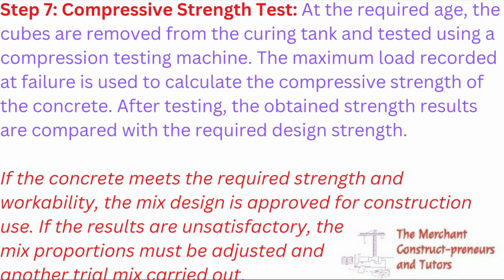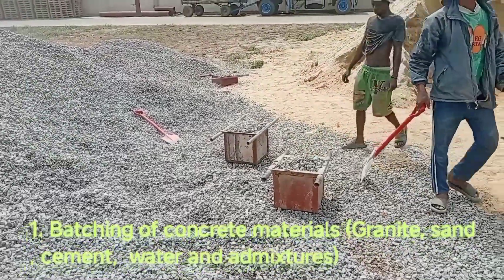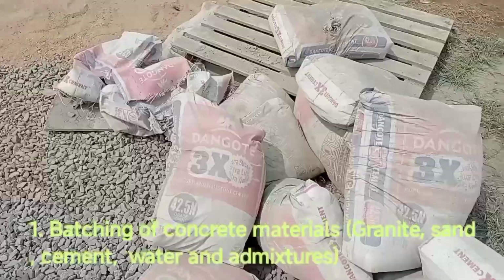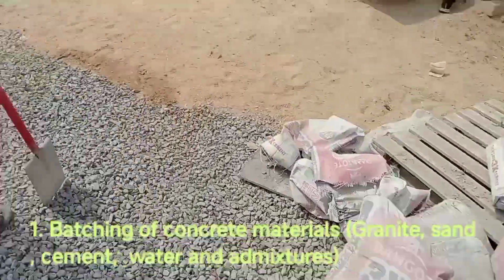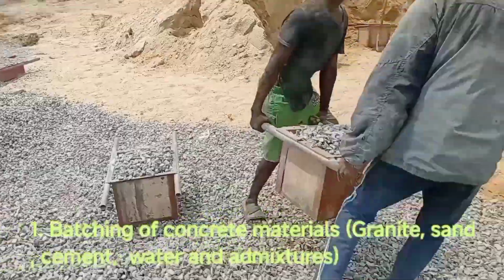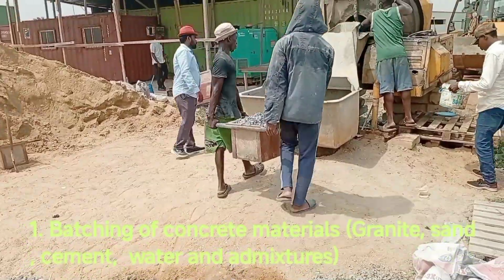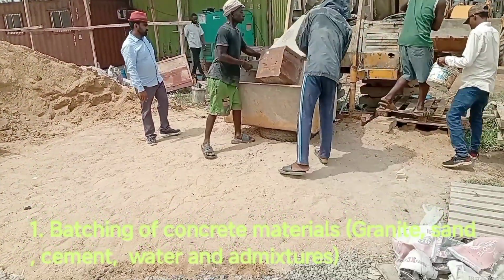And what most consultants do is, this trial mix you are going to do for like 3 batches, and each batch contains 6 cubes. So 6 cubes, 6 cubes, 6 cubes, that's like 18 cubes. The same mix ratio, but from different batches of concrete. If you batch this set of concrete, you cast the first 6. You batch another one, you cast the next 6, using the same ratio and water cement ratio. You batch the last one, the same thing. So we ensure that everything is in line.